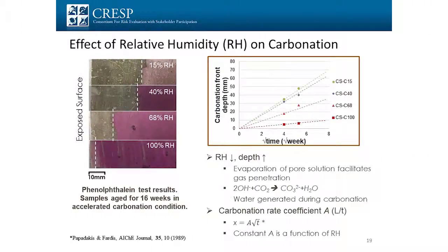So the next two plots, I may have accused the student of making these data up because the variability is so small, the uncertainty is so small, it was hard to believe. This one is looking at the effect of relative humidity based upon the carbonation effect. You can see you have a fairly linear, with square root of time, effect of relative humidity on the depth of carbonation.